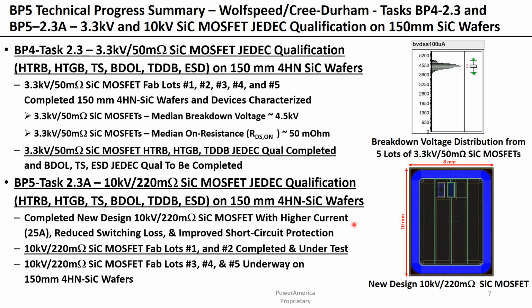We've completed the new design of the 10 kV, 220 milliohm silicon carbide MOSFET shown here to the right. It has lower on resistance and higher current rating, reduced switching losses, and improved short circuit protection. We've completed 2 fabrication lots of 10 kV, 220 milliohm silicon carbide MOSFETs on 150 millimeter wafers, and these are currently under test. And there are 3 more 150 millimeter fabrication lots of these 10 kilovolt, 220 milliohm silicon carbide MOSFETs that are currently underway.